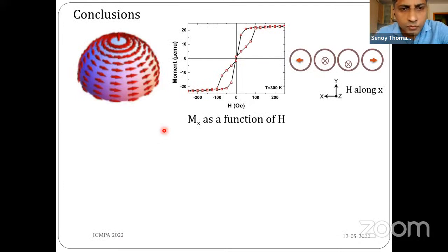Okay, so as a summary, we have seen vortex structures in nanocaps, which could be considered as two-dimensional magnetic vortex structures, where if you apply a field along the in-plane direction, there will be negligible remanence and coercivity. Basically, once the vortex core is nucleated, it moves perpendicular to the direction of the field. And in 3D vortices,